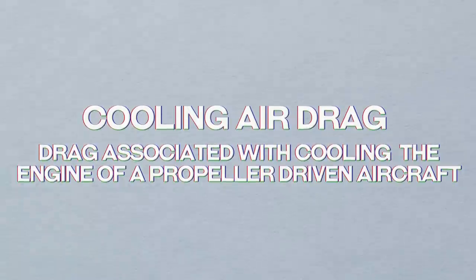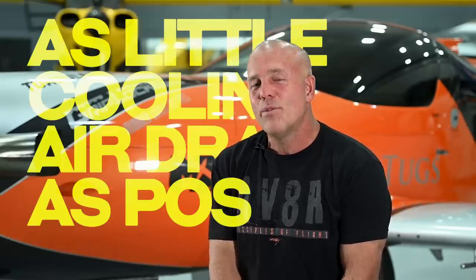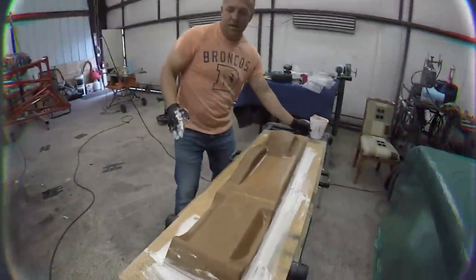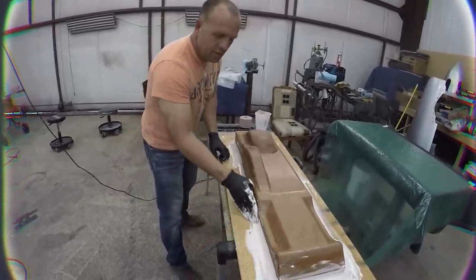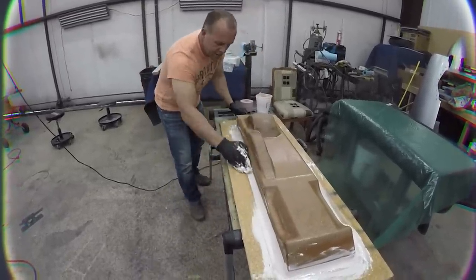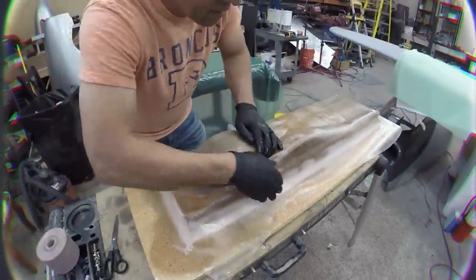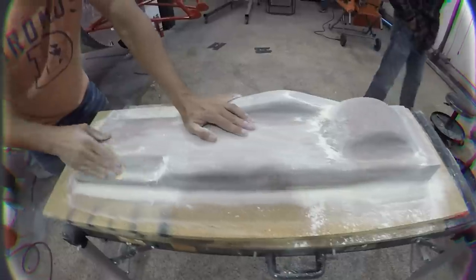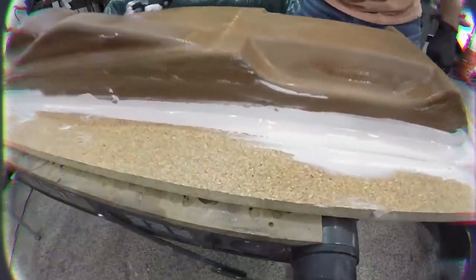There's a lot of speed lost on hot rod airplanes from cooling air. Cooling air is almost like a swear word in air racing — you want as little cooling air drag as possible. This mold is a couple of inches taller than it needs to be so you can trim off the carbon fiber. The hard 90-degree lines on the bottom are too hard to work with to get the mold to release. So we're putting micro in it, rounding the edge off so it'll be easier to pull off. We're going to put one layer of fiberglass over the top of this wood, sand it smooth, build a little bodywork on it, and then that will be the surface we lay carbon fiber onto.